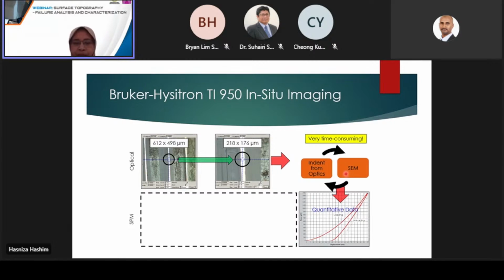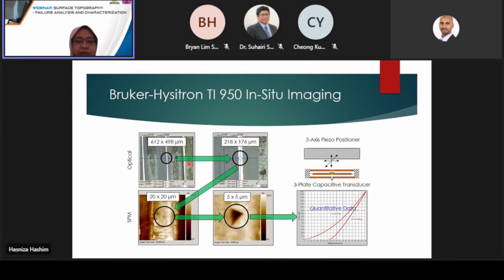So in the past, people had to go back and forth between SEM and the Nano Indenter to confirm the correct placement of very small nano indentation, which is a very time-consuming process. However, with the in-situ imaging, we can locate the area where we want to do the indentations by using the optical microscope. Then we use the SPM to do the imaging before we do the indentations. And then once we do the indentation, we can also re-image the area of indentation so that we can check the quality of indentation, whether we have done the indentation in the correct way, at the correct place.